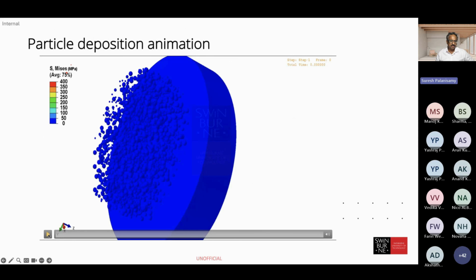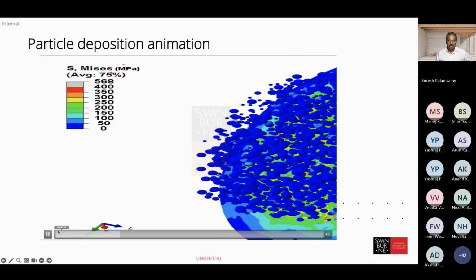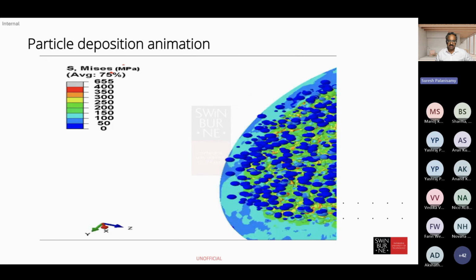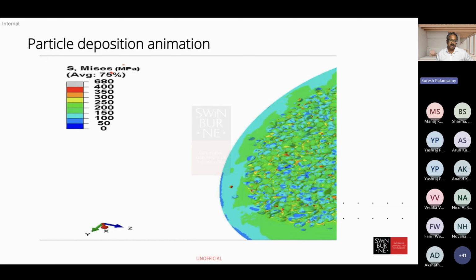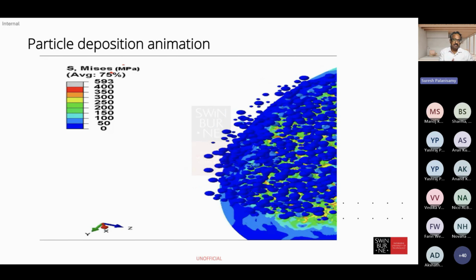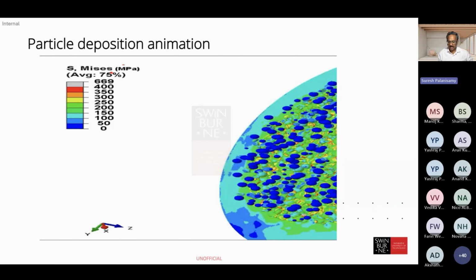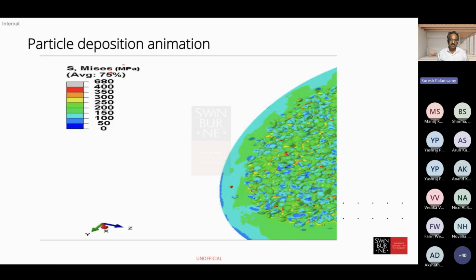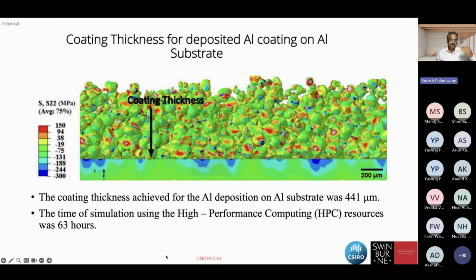So this is an example of the work carried out by my student: particle deposition, 10,000 particles deposited on a substrate. It gives an idea of how many particles embed and how many bombard the substrate, because each particle is a different size or shape and carries a different mass, and obviously a different velocity it is propelled at. So it creates a different bonding mechanism and also bombarding. As you can see, this is the coating thickness achieved. And as I said before, even using high performance computing resources, it took 63 hours just for a small layer, a 441 micron layer thickness. It took 63 hours of supercomputer time to do the simulation.